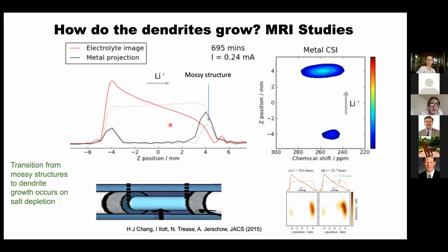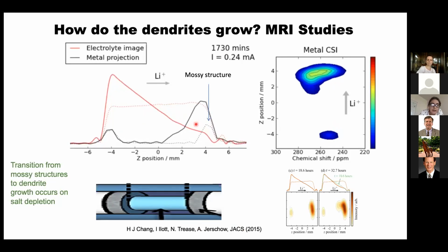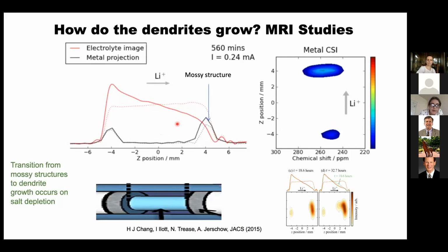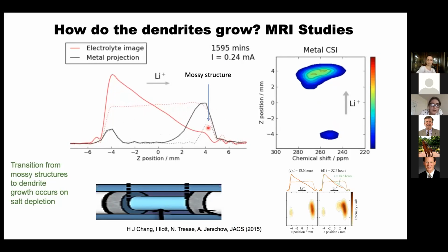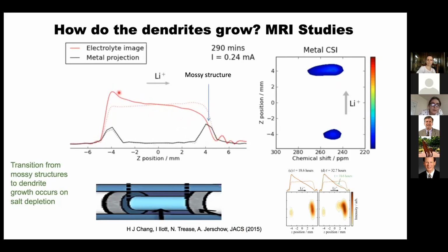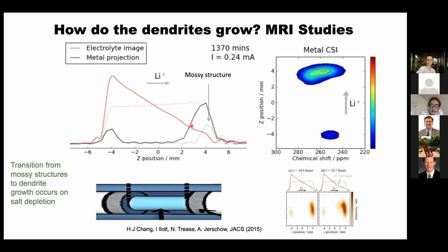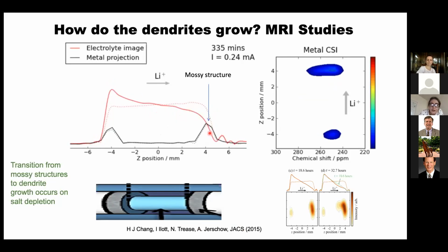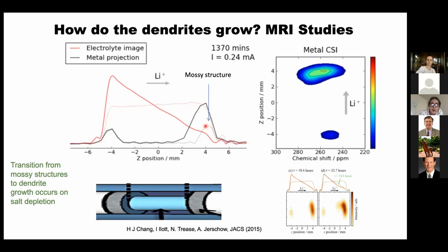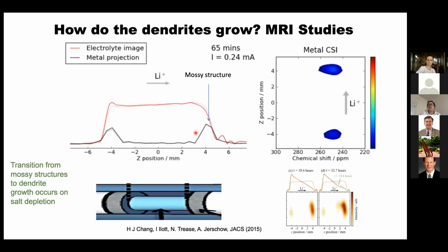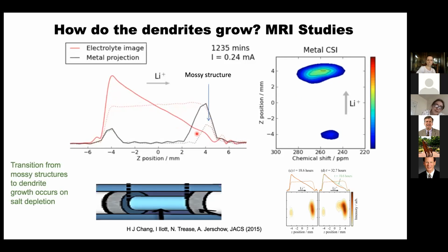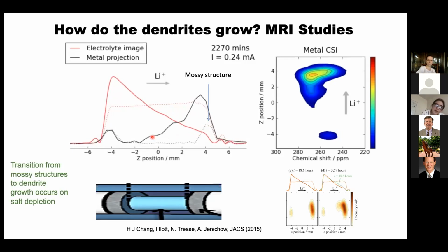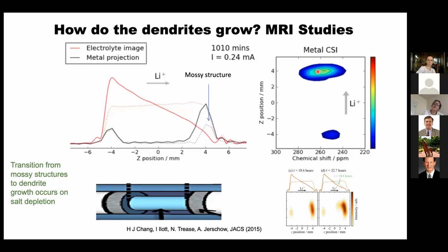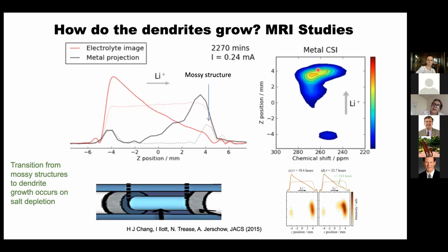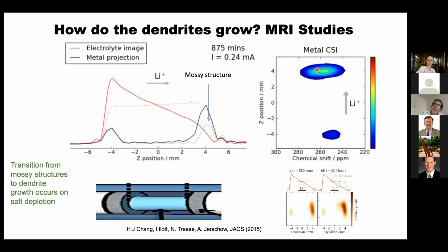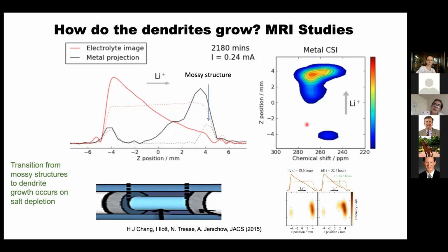So the lithium ions go in this direction, and the counter anions, in this case, the PF6 I was talking about, they flow in this direction. The lithiums deposit, the PF6 can't, and so you build up a concentration gradient. Okay, so now watch the lithium metal. What you first of all see is the lithium growing up in these mossy structures, but when the concentration gradient hits 0, you get a space charge or an electric field that drags the lithium metal out, and you form dendrites. And you can see this more clearly in the so-called chemical shift imaging. So this is again the lithium mossy structure that grows, and then when the electrolyte drops, you get dendritic.